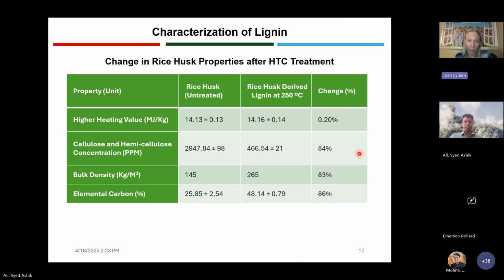There we go. We also checked some other things that would be of interest. We looked at the fuel value, and that did not change a whole lot with hydrothermal carbonization. We looked at the cellulose and hemicellulose concentration before and after, and we saw way lower amounts of cellulose in it, an 84% reduction in cellulose for the biomass. Our bulk density also went up, so you could put a higher weight of it into a truck after you had done the HTC to it. And we also got greater elemental carbon. So we can go on to the next one.